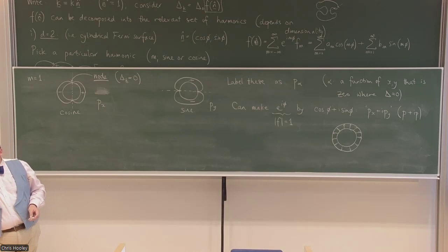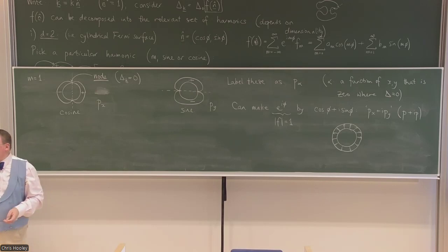A curiosity is that, we were discussing on Wednesday how fully gapped states are generally preferred. So you might think that nature would tend to go for these gaps that don't have any nodes. And actually, a surprising number of materials do have nodes, and I'm not sure I really understand why that is. I would expect from general thermodynamic arguments that things like p plus ip or d plus id would be much more common than just one of the real harmonics, and they don't seem to be.